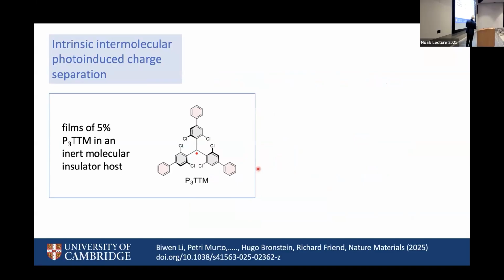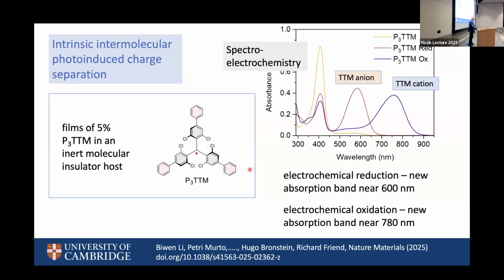People work on a P3TTM, we published it recently. So the molecule happens to have phenyl groups around the edge, and if we bring them close enough together, the phenyl groups provide some intermolecular contact. And what we hope is when we absorb photons, we will see both electrons and holes appear magically, because that's the lowest lying excited state. So what we can do is to look for a color change. And what you see on the left is what happens if we oxidize or reduce electrochemically. The absorption at about 450 nanometers is quenched as we oxidize or reduce. If we reduce, we see an absorption band at 600 nanometers. If we oxidize, we see one at 750 nanometers. That's the sanity check that we know what charges look like.